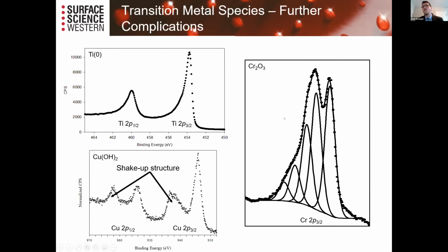Over here we have chromium 3 oxide, and we have this complex peak shape for chromium 3 oxide. And one of the things we saw in the literature was that people would take a look at this and say, okay, instead of saying this is the multiplet structure of chromium 3, they would try to assign and say, okay, this is chromium 2, chromium 3, chromium 4, chromium 5, chromium 6. And some of these species don't realistically exist, or they're very rare. So we're seeing those kinds of errors in the literature.